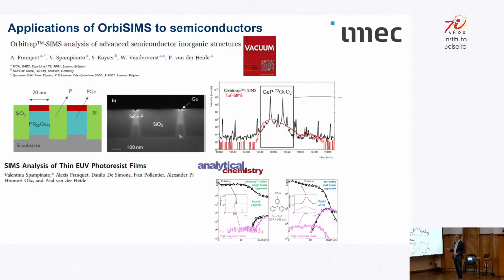whereabouts it came from. So for example, in this device here, you have silicon dioxide, you have germanium, phosphorus, germanium phosphide. If we look at the time of flight SIMS spectrum, which is the red curve, so this is the work from IMEC, by the way, Alexander Franquet and colleagues at IMEC, it's not from my group.